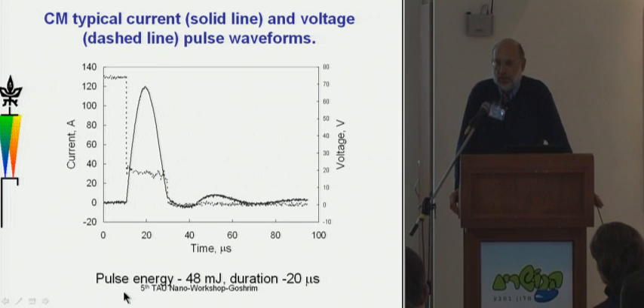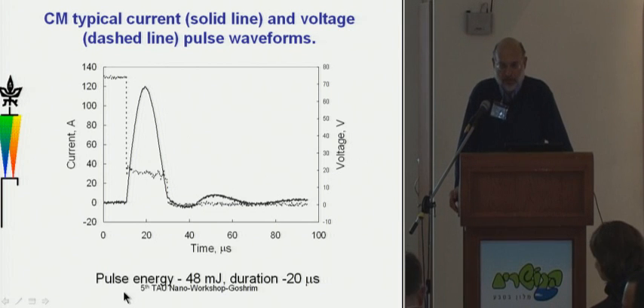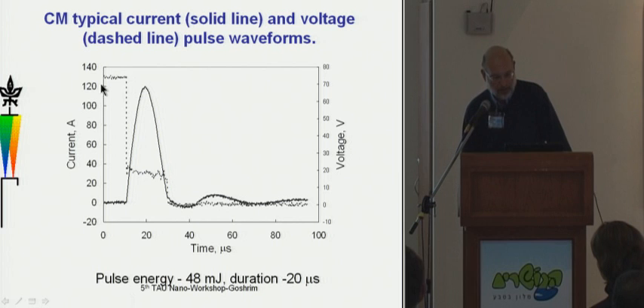This is an oscillogram of the current and voltage through the discharge in the contact mode. This dotted line is the voltage. The capacitor was charged, in this case, to about 75 volts. When contact was made and the arc was drawn, it drops down to the typical arc voltage, in this case of around 20 volts. And it produces a current pulse of about 20 microseconds duration and a peak current of about 120 amperes.